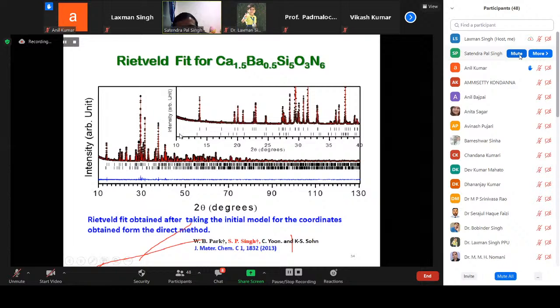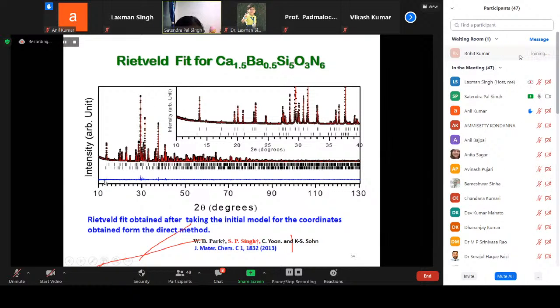So in this Rietveld fit, what do we have? The red line is the calculated line. The black line is the observed line that you obtain from the XRD pattern. And the vertical black lines are the positions of the Bragg reflections. If you see this picture, it is a very beautiful match. The red line coincides exactly with the black line, and this is the difference profile, nearly flat. So the structural model which we have solved is very well matched with the observed profile.